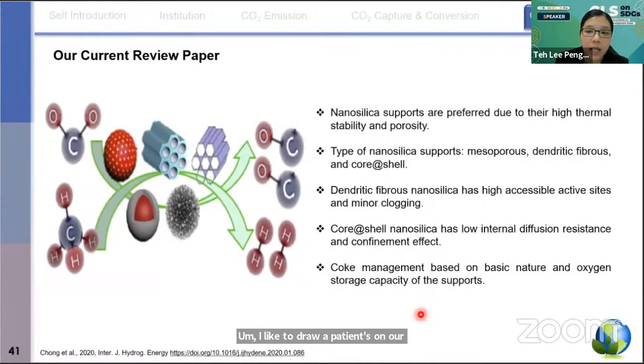I would like to draw your attention to our recently published review paper on nanosilica-based catalysts for syngas production via the CO2 reforming of methane. Nanosilica supports are preferred due to their high thermal stability and porosity. In this review, we discuss mesoporous nanosilica, dendritic fibrous nanosilica, and core-shell nanosilica. From there, we conclude that the dendritic fibrous nanosilica has high accessibility and minor clogging, while the core-shell nanosilica has low internal diffusion resistance and possesses a confinement effect.